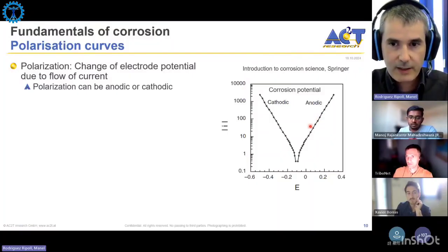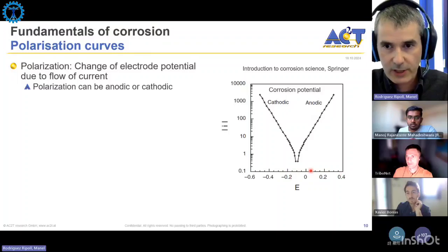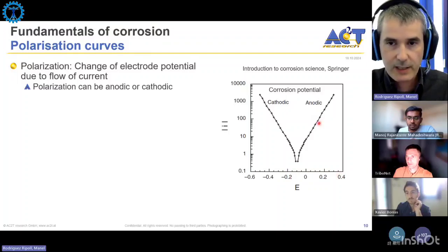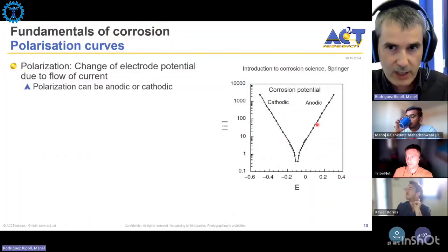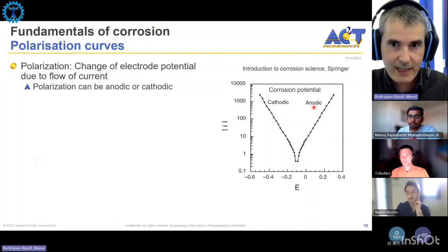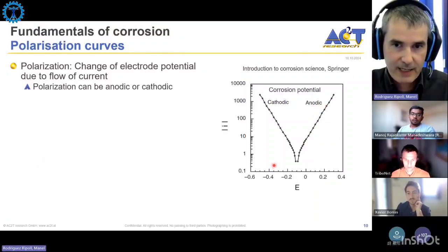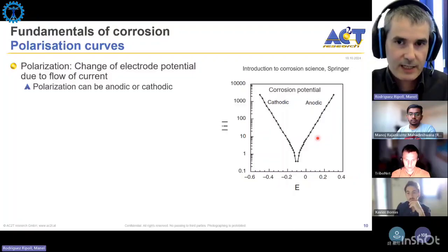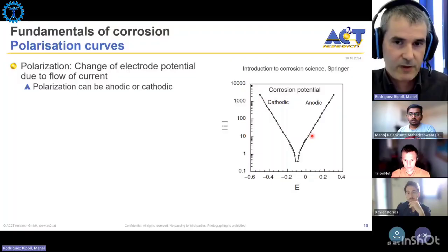And if we go in this way, so if we put an anodic potential, then what we are doing is that we are removing electrons from the metal, so we are promoting the anodic reaction, so we are increasing the corrosion of our metal. And if we apply a cathodic potential, so we put a negative potential, basically what we are doing is we're supplying our metal with electrons, so what we are promoting is the cathodic reaction at the surface of the metal, and then we have an increase in the current that is dominated by the cathodic reaction.